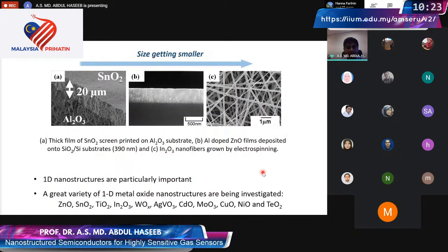Just to give you some idea what we mean by reducing the dimension. In early years, a few decades ago, the gas sensors were used in thick film form, where we have tens of micrometers of oxide used as the gas sensing elements. Then the trend was towards using a thin film, where we have a few hundred nanometer thickness. And now the trend is towards producing the nanostructures, which are much finer in size, just a few tens of nanometers. For instance, we have now these nanowires of few tens of nanometers.